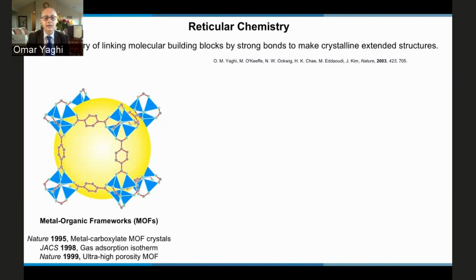And unlike any other metal organic structure preceding these, MOFs were made from negatively charged linkers, such as terephthalate, linked by metal ions, in this case a tetrazinc unit being linked by the carboxylate. This charged linker, the negative charge on carboxylate, and its bonding to the metal ion produces a strong bonding, in some cases as strong as carbon-carbon bonds.